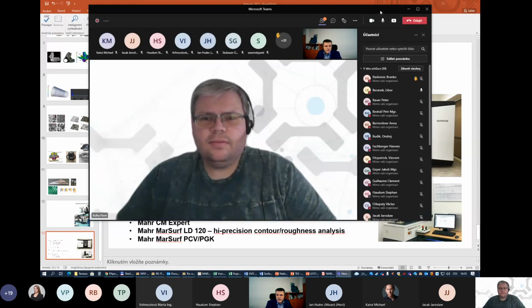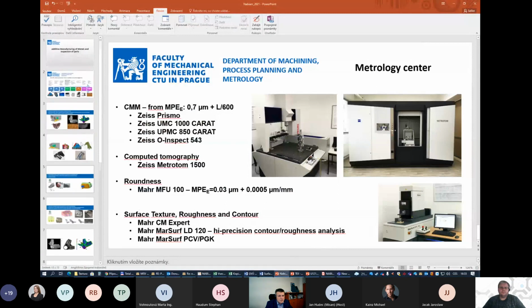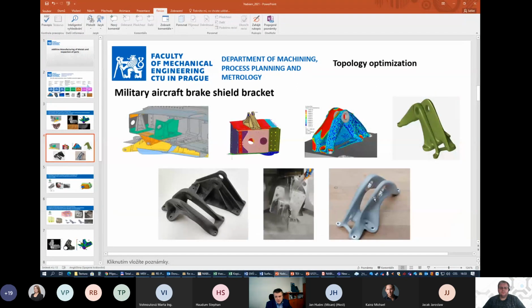I would say every time where the part matters, when it has to be installed somewhere where you need precise specifications. On the printer, when you see the part, maybe the bracket, this is the typical part. Quite a big part, like 200 millimeters across. I hope the image is still available to you. The deformation of the part after printing is sometimes even close to a millimeter. So then you have to be able to manufacture all these surfaces which have to be assembled with the counterpart, and you want to have the specifications far more precise than 1 millimeter, for example 0.1 millimeter or 0.05 millimeter, then you usually have to machine it.